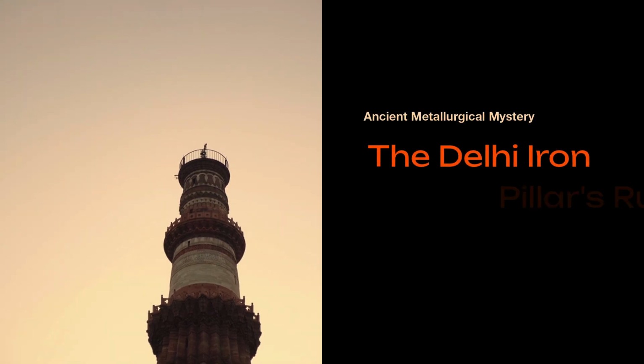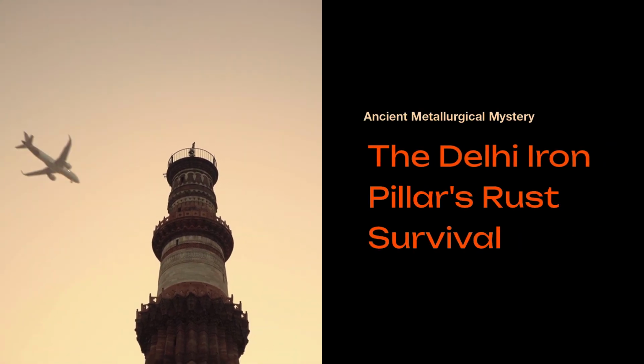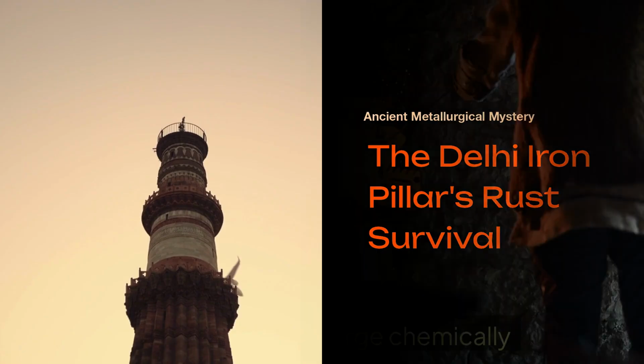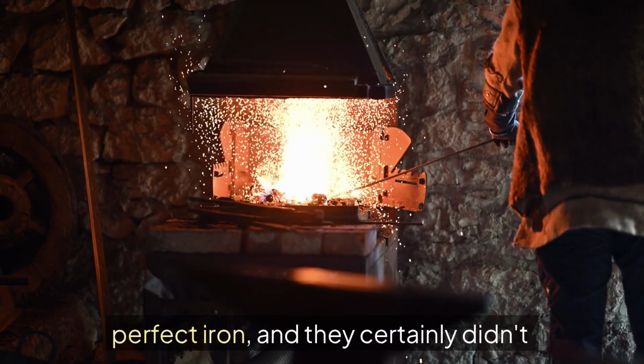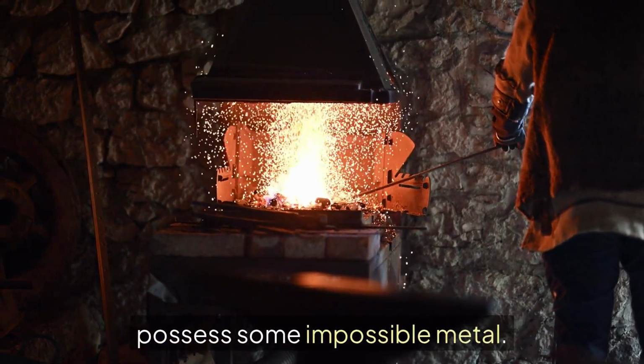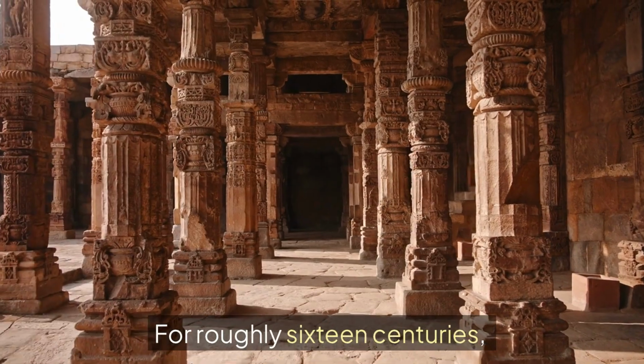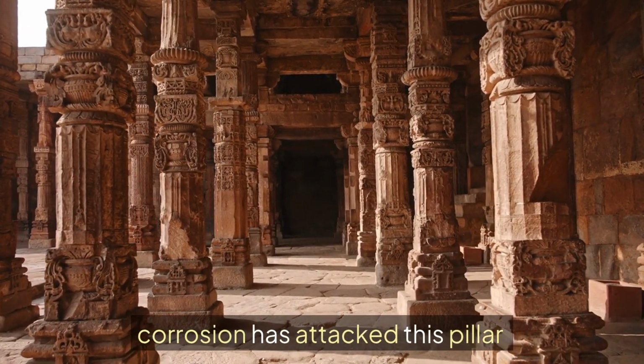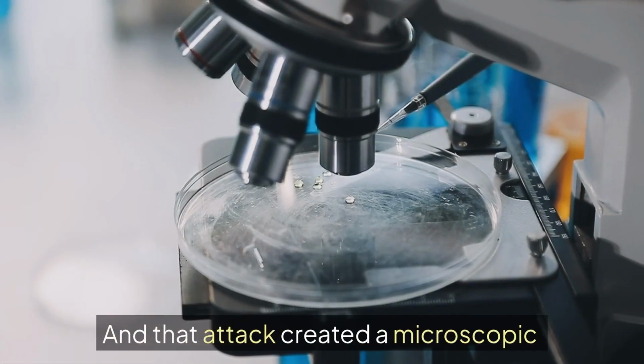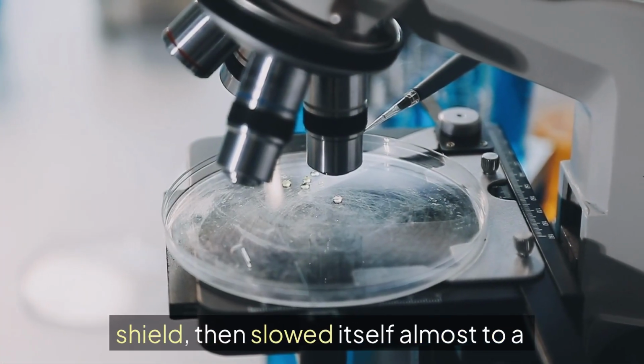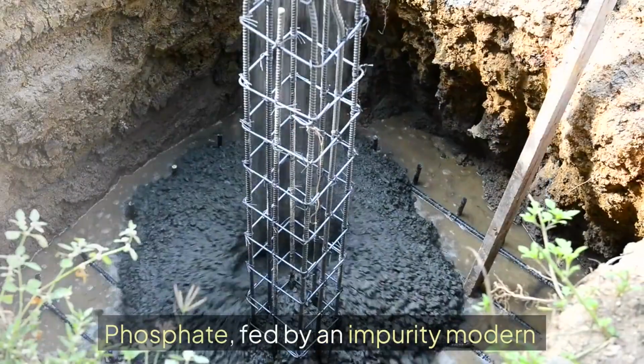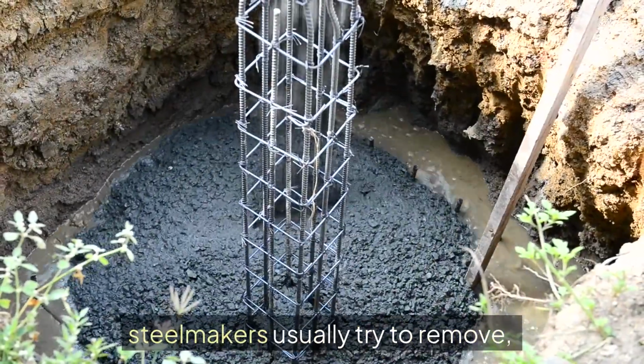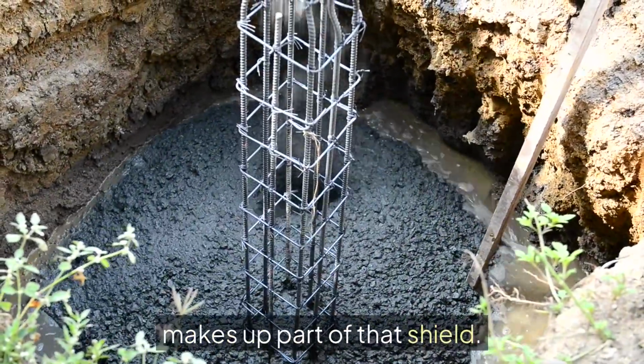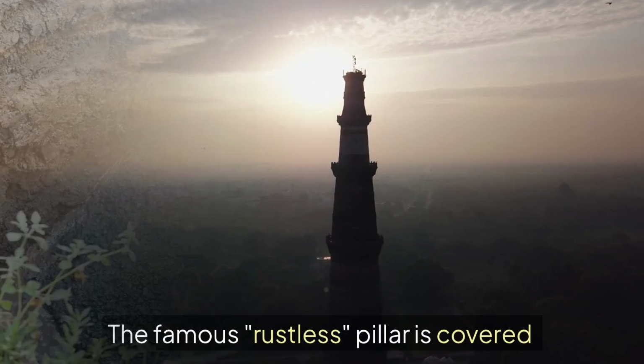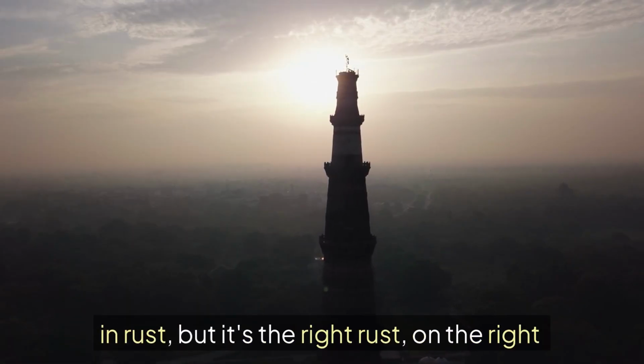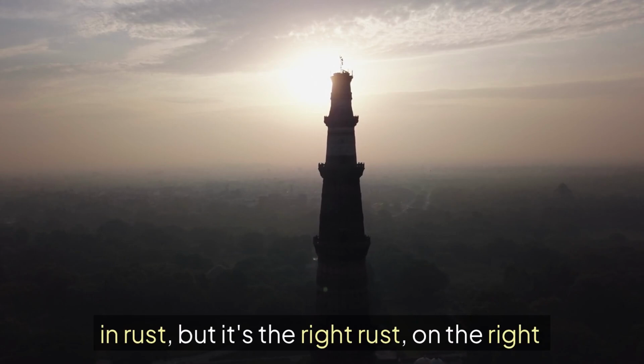The Delhi iron pillar has survived because it rusted, not because rust somehow missed it. Its makers didn't forge chemically perfect iron, and they certainly didn't possess some impossible metal. For roughly 16 centuries, corrosion has attacked this pillar outdoors, and that attack created a microscopic shield, then slowed itself almost to a standstill. Phosphate, fed by an impurity modern steelmakers usually try to remove, makes up part of that shield. The famous rustless pillar is covered in rust, but it's the right rust, on the right iron, under the right sky.